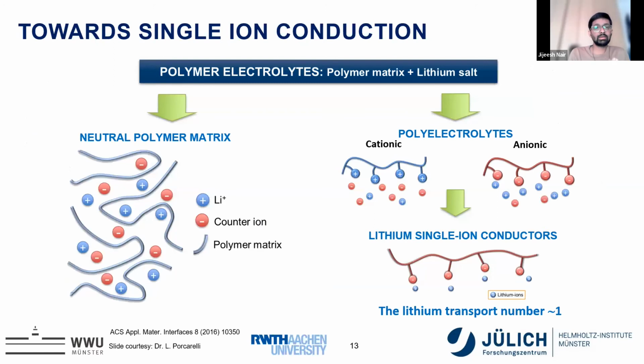Then, as I mentioned again, there is polymer plus salt, which you can call a neutral polymer matrix, which is PEO along with this one. But the newer development is to improve the lithium-ion conductivity and improve the percentage of lithium ions that is transferred within the polymer matrix, which is called polyelectrolytes, in which the polymer backbone can bear a charge.